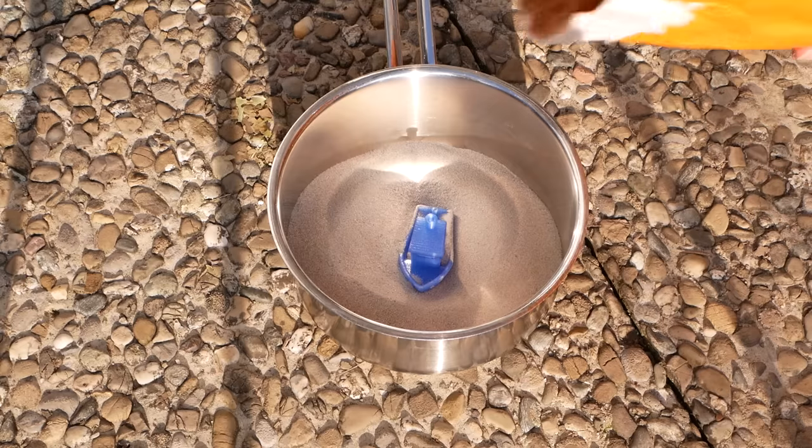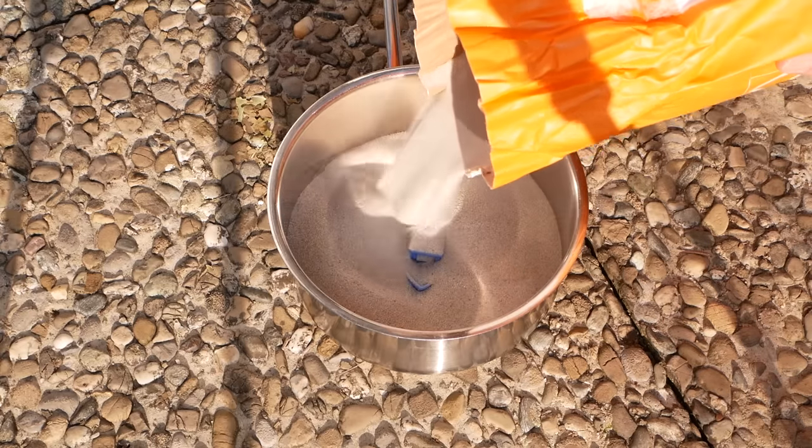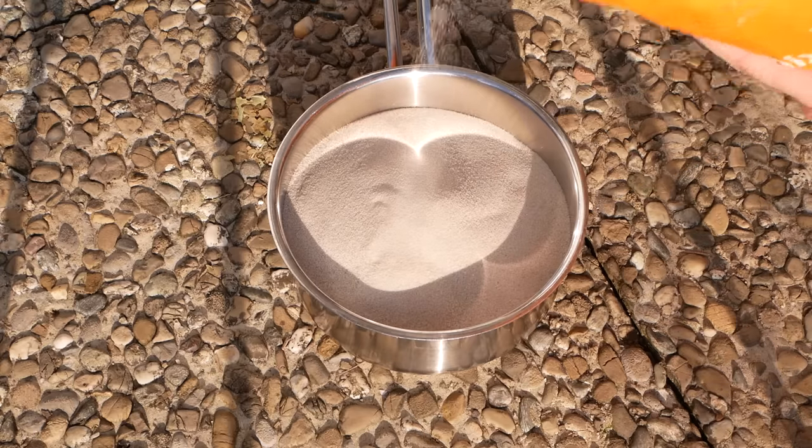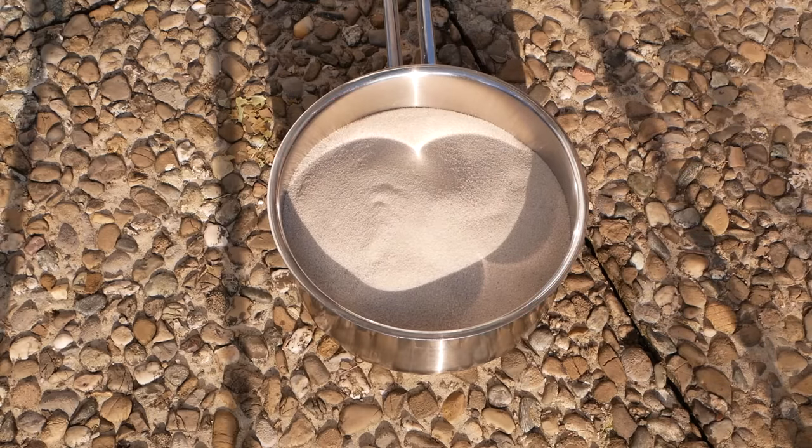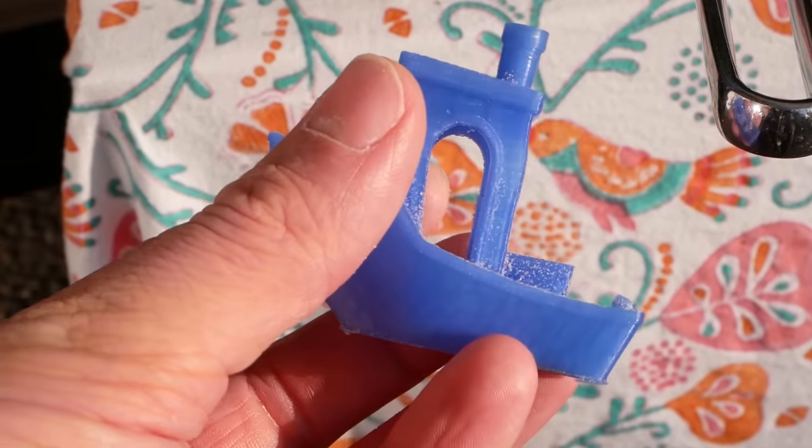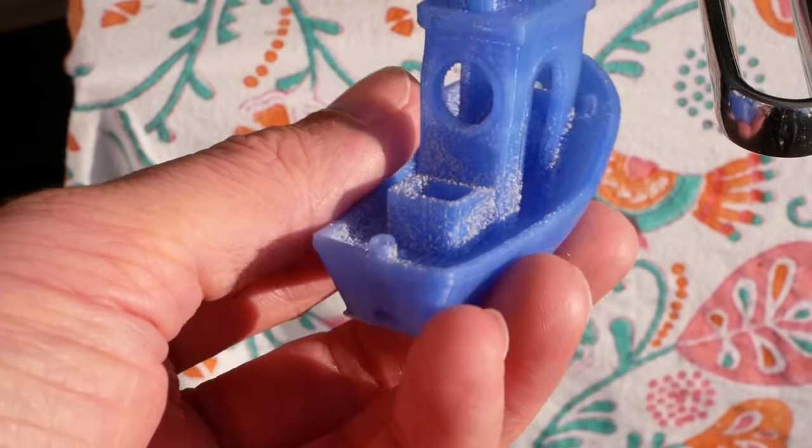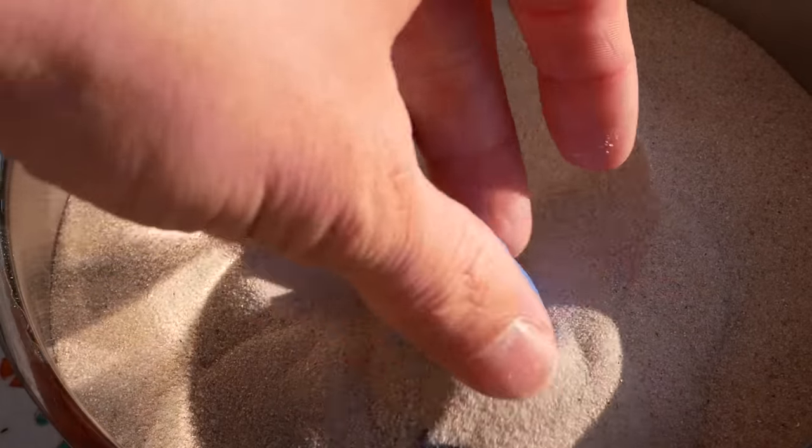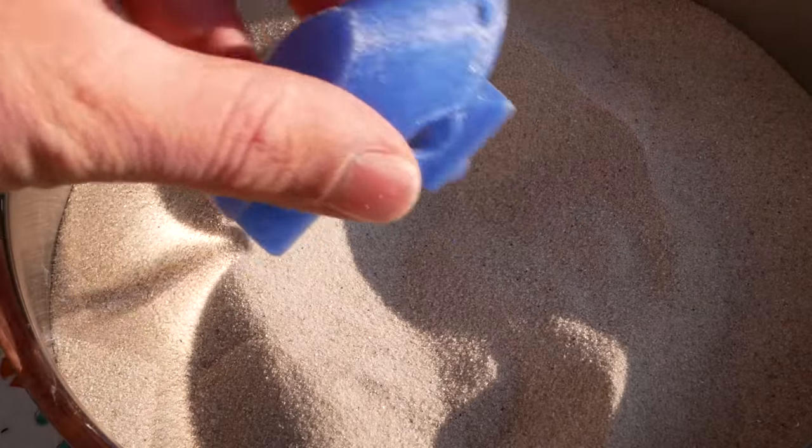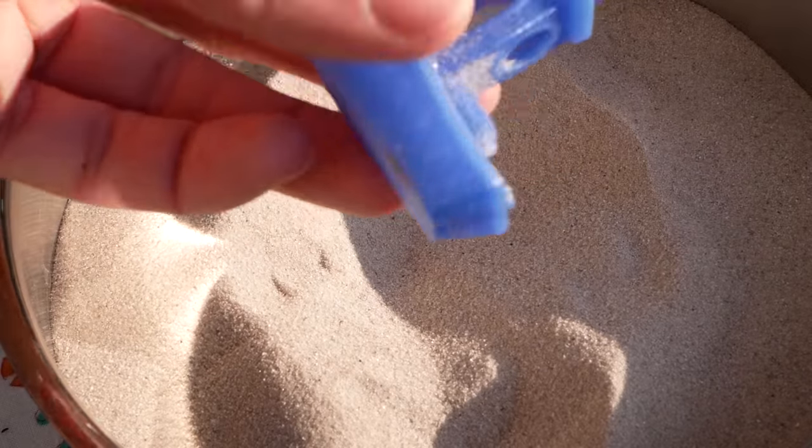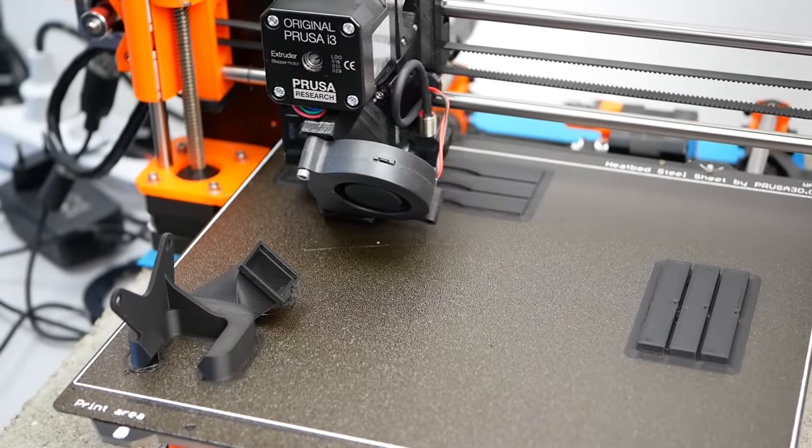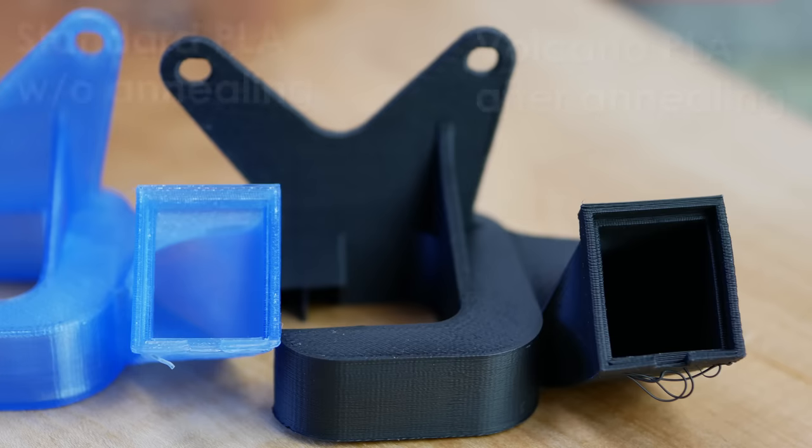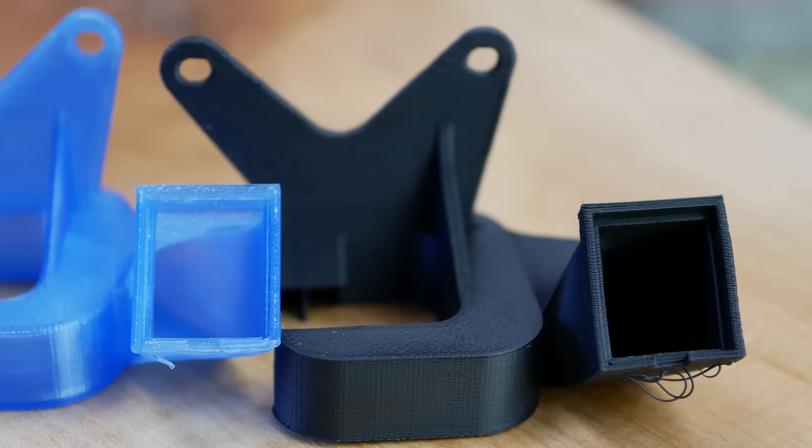Another one that I tried out is submerging the parts in sand. I tried that in a couple of pre-tests where it helped a bit but not to the point that it totally eliminated warping. I'll probably try it in the future with a bigger container so that the parts are more thoroughly held in position. Due to the thermal mass and the isolating properties of the sand, this might be a possibility to even out the temperature changes if you have an oven that is not properly controllable. There are also specialized materials like Form Futura's Volcano PLA around that barely warp during the annealing process but still are able to improve the heat resistance significantly.